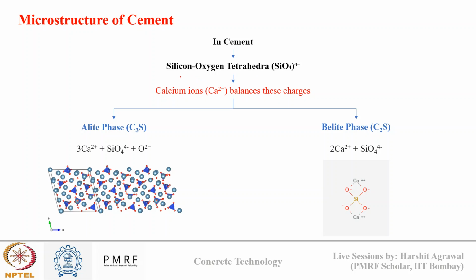Okay, so we know that there are negative charges which are unbalanced on the silica tetrahedra. Now, these charges must be neutralized by some compound to form a stable phase. And in cement clinker, the calcium ions are there which balance these negative charges. In belite, you can see there are two calcium ions which give us a +4 charge, which balances the -4 charge present on the silica oxygen tetrahedra, and this results in the formation of C2S.